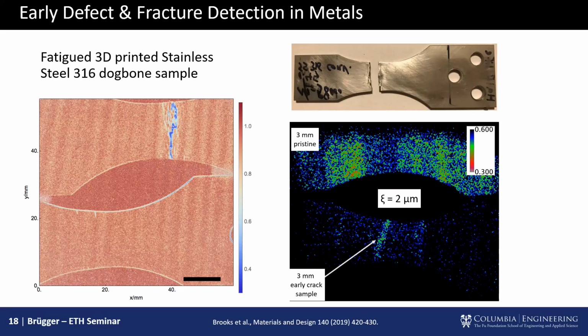I can build gratings, throw them in the beamline, and then you can see on this dog bone sample initiation of fractures essentially in the nucleation stage. So at that point, there's no visible fracture there. This is just nucleation. That, of course, is very powerful.